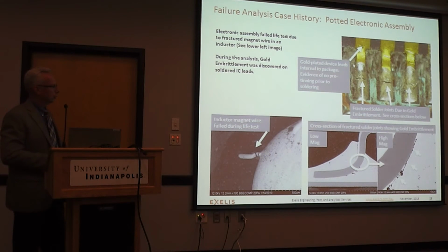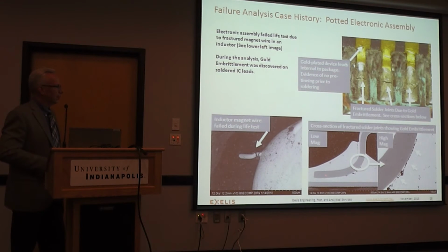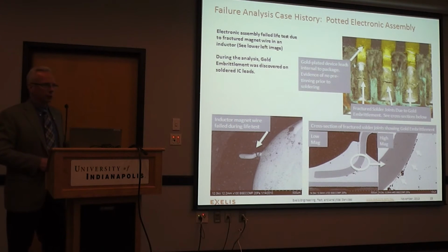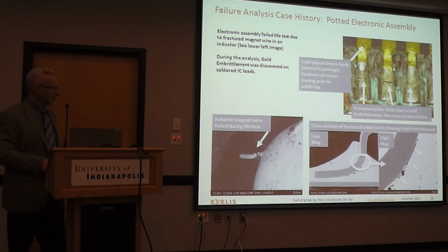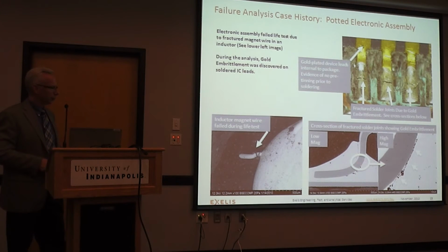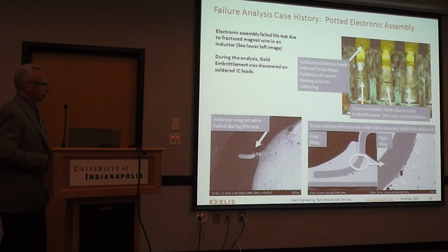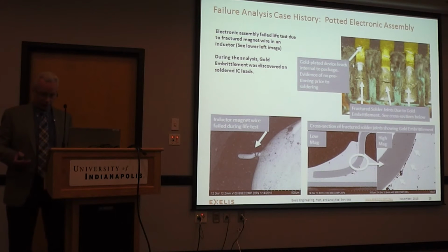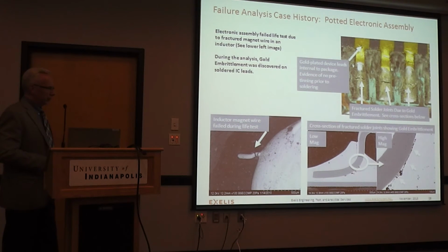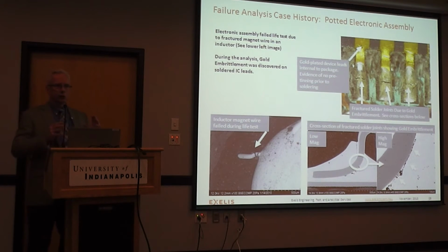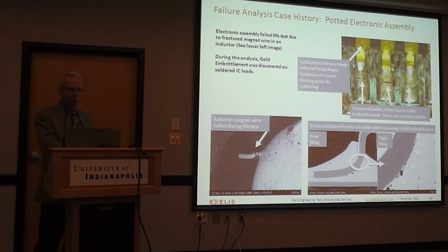Okay, now we're going to show you a little bit of metallurgy here. Going down to this lower right-hand image, this is a cross-section of the lead going into the solder joint. This bottom layer here is the pad on a printed circuit board. Okay, and then the light material is the solder joint. And then we have a higher mag image of this area of interest. And now you can see a fracture path following the surface of the lead. And if we went into even higher magnification, what you would see gold tin intermetallic crystals preferentially following that gold-plated lead.